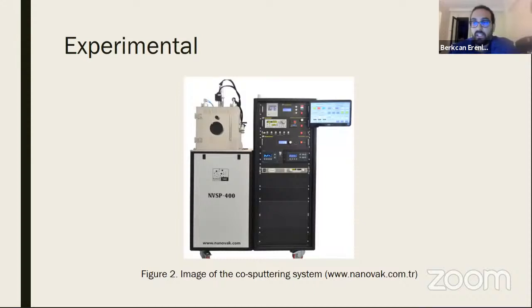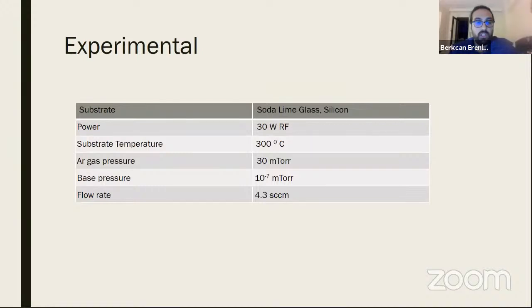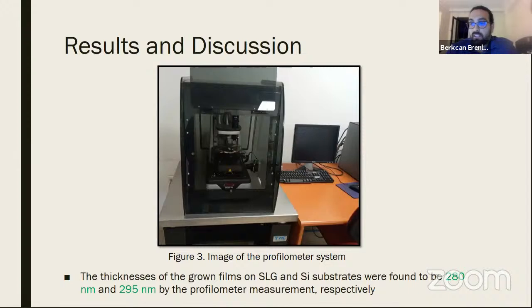Image of the co-sputtering system. This system we use. Our deposition parameters: substrates soda lime glass and silicon, power 30 watt RF, substrate temperature 300 degrees Celsius, argon gas pressure 10^-7 millitorr, flow rate 4.3 sccm. The thicknesses of the grown films on soda lime glass and silicon substrates were found to be 280 nanometers and 295 nanometers by profilometer measurement. This system belongs to us, the Photonic Application and Research Center.